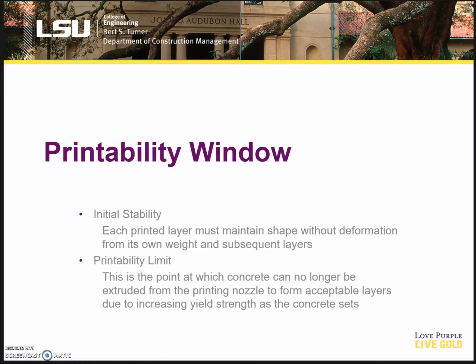The initial yield stress usually increases over time in a linear fashion up to its set point. And the same reason that it starts to gain strength is the same reason there's a printability limit. This is the point at which concrete can no longer be extruded from the printing nozzle to form acceptable layers. If you leave the concrete in the printer too long, it'll set and probably ruin your printer, or at least the nozzle, because you have to get everything out.